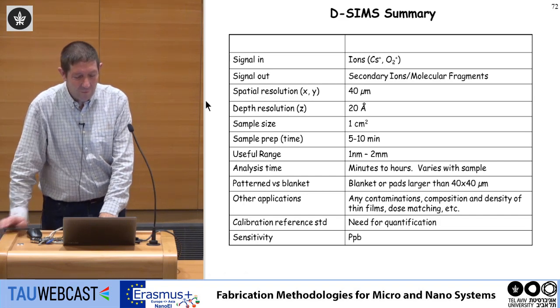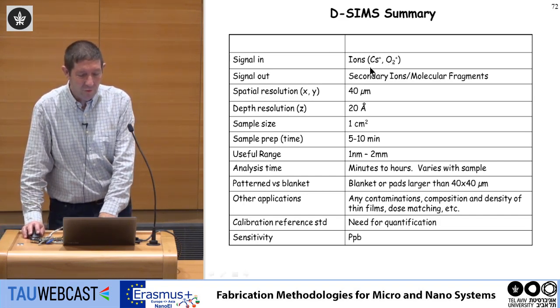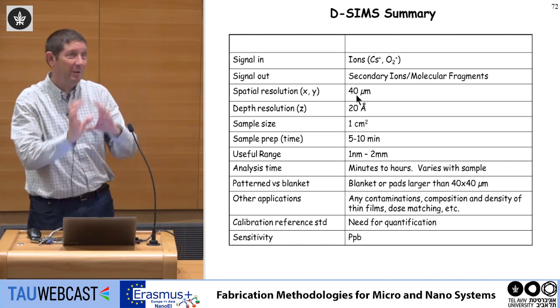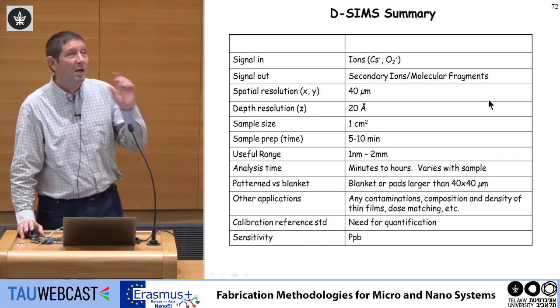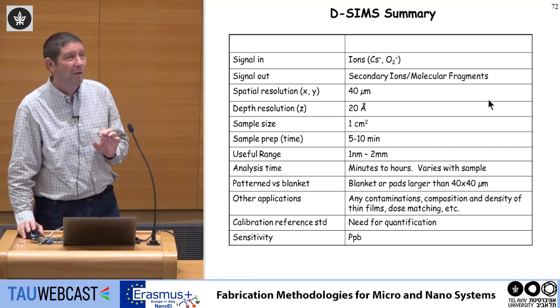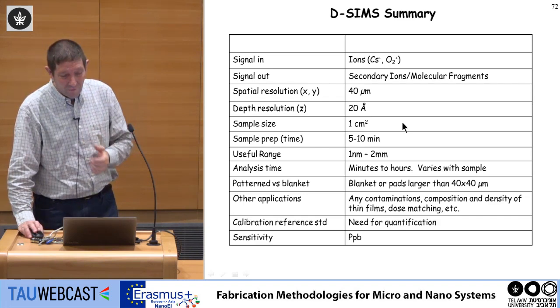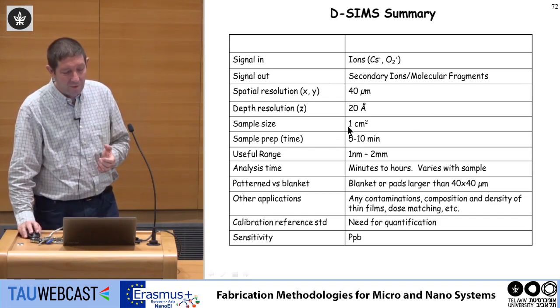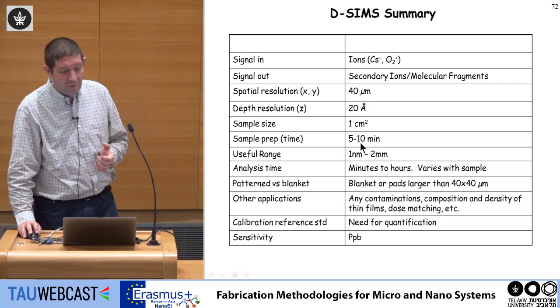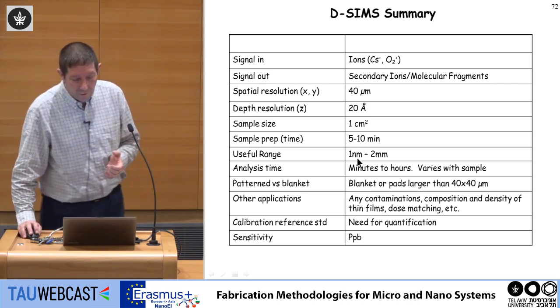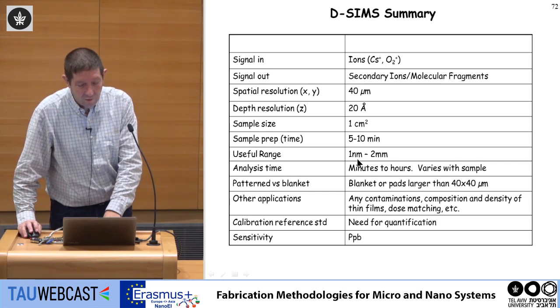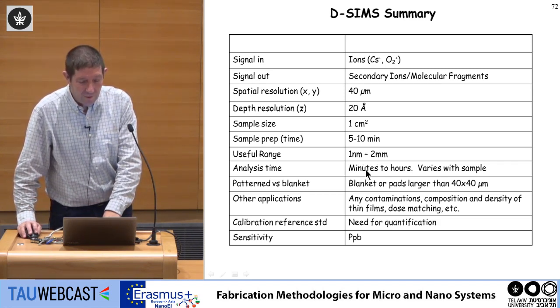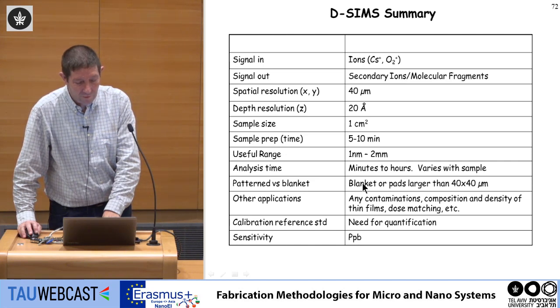So this is the SIMS. You measure ions using either cesium or oxygen, and you look at the secondary ions. Spatial resolution is very coarse. It's like 40 microns and more because the beam is pretty big. So it's not high resolution, even though there are some systems which are high resolution, but it's not so common. Sample size is not so large. It's a 1 centimeter square. Not complicated to prepare. And the useful range is 1 nanometer to 2 millimeter. And it takes minutes to hours, depends on the quality of your system. And you can do it on wafer, blanket, or pads larger.